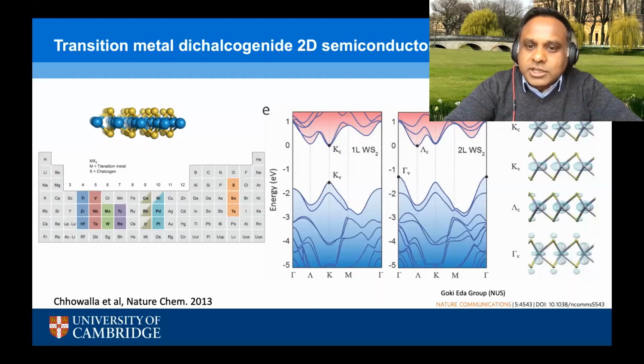And if you look at the band structure, even in their multi-layered form, they're reasonably sized band gap semiconductors. This schematic is taken from Goki Eda's group at NUS, where they showed that the weak interaction between the layers gives rise to these states at the gamma point in the valence band. And so the energy minimum in a multi-layered system is between the gamma point and the lambda point, making it an indirect band gap semiconductor when you have more than one layer. But in the monolayer case, the absence of the interactions between the layers transitions the material into a direct band gap semiconductor. And this makes it very interesting for optoelectronic applications. Of course, one can also see that the valence band has a split, and so that gives rise to different states in different valleys, and the splitting is large enough that we can access those valleys as well.